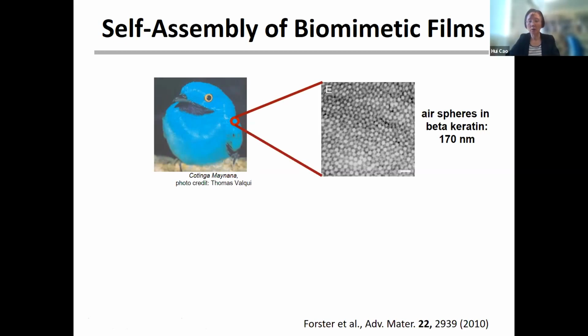But they don't want a long range order, because if you have a long range order, then the period will be different at different angles, and that will make an iridescent, angle-dependent color. So to make an angle-independent color, they cannot have long range order, so they have only short range order. On the long range, there's no order here. This allows them to have isotropic structures that give this kind of isotropic color. So it's a pretty smart design. Now we understand what's going on.